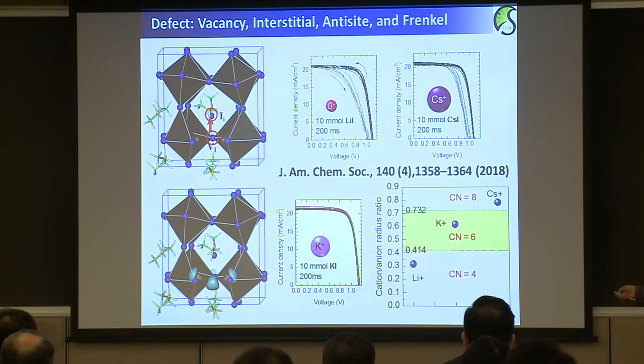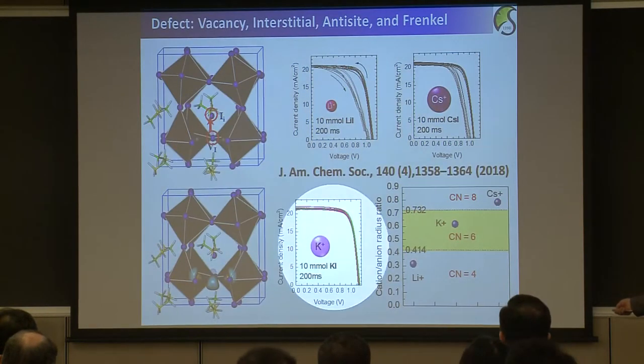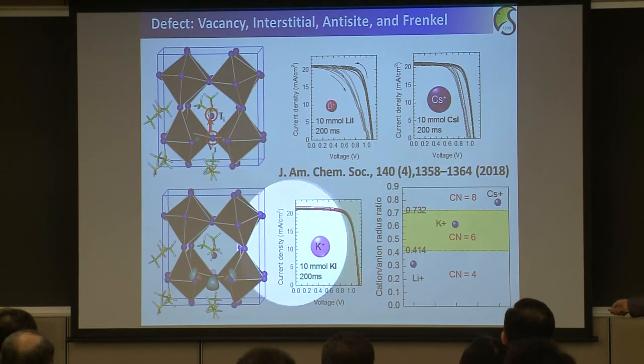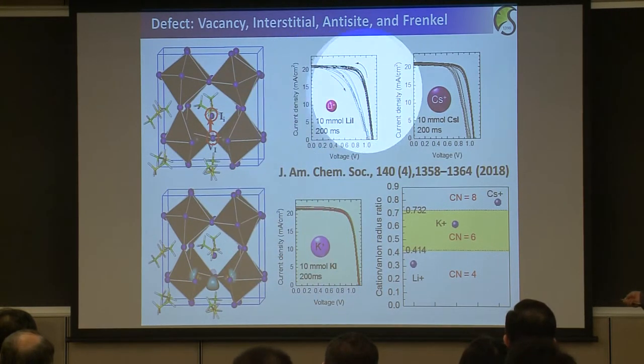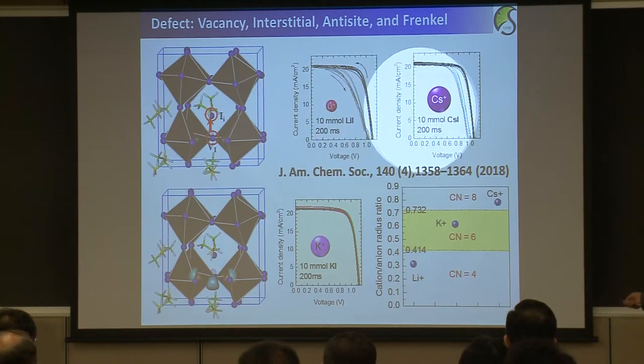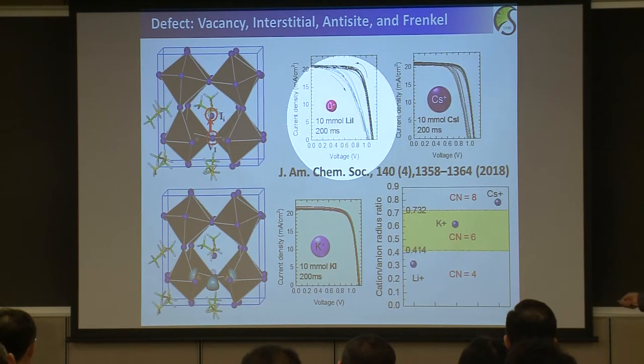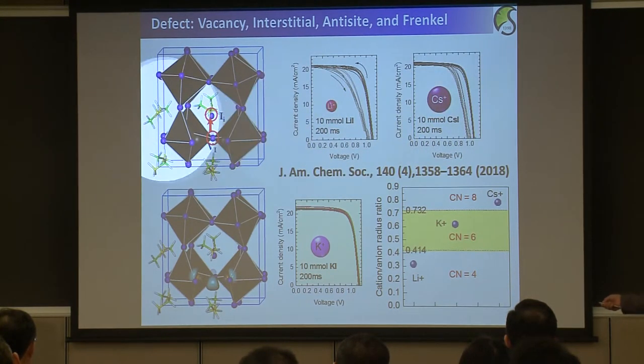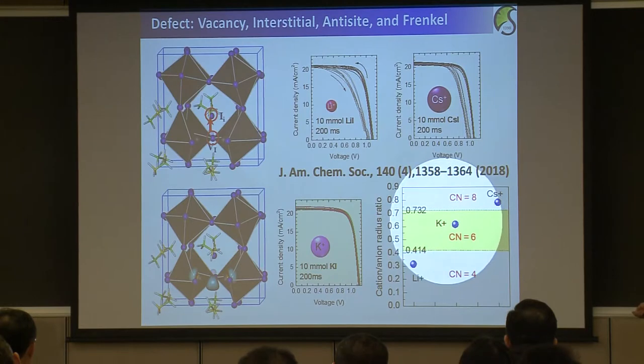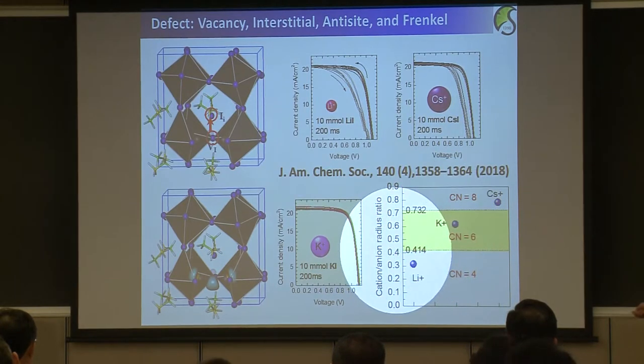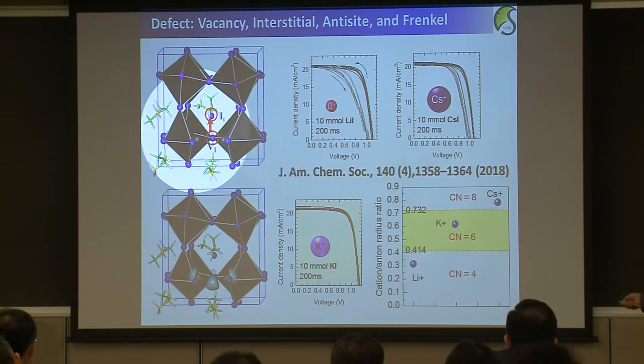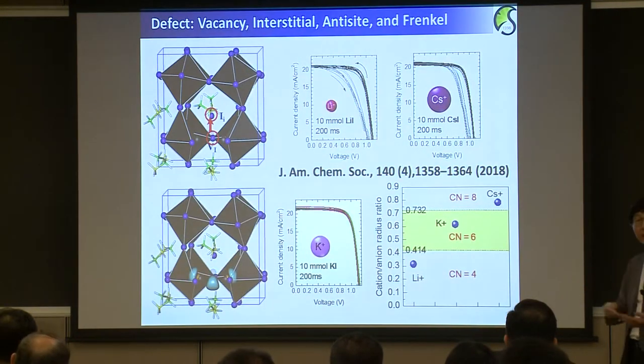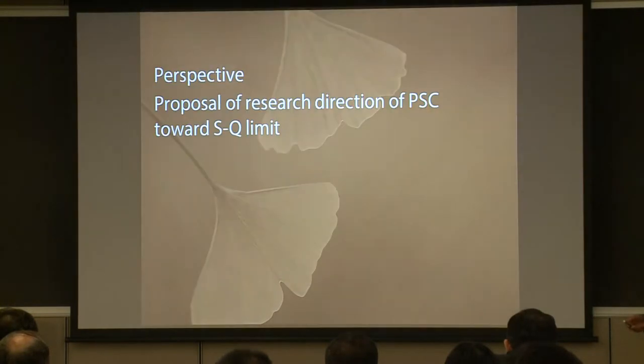Therefore, you can remove the IV hysteresis. Well, for instance, why lithium and cesium cannot remove the IV hysteresis? Because lithium is too small, cesium is too large to accommodate in this interstitial site. So by using a very simple cation anion radius, this interstitial site is octahedrally favored site. So potassium iodide is working well.